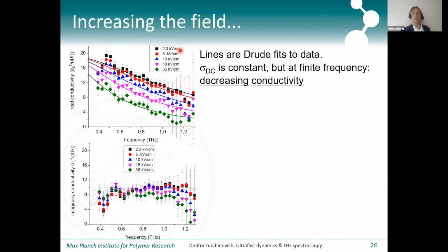Now, as we increase the field strength, even as it goes up to a few tens of kilovolt per centimeter, you see that the real conductivity drops pretty dramatically. The imaginary conductivity does not drop as quickly, but this is all consistent. But the most important thing is that at, say, 40 kilovolt per centimeter, you can see that the conductivity at, say, a terahertz, which would be a typical operating frequency, has dropped by a factor of 3 already.